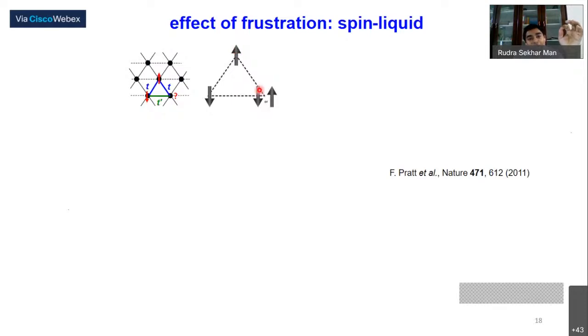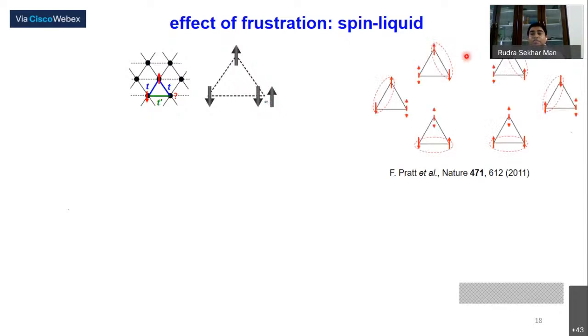And if you put down here, then this interaction is antiferromagnet, which is fine, but that one is ferromagnet. It's a problem, because I told you the ground state should be antiferromagnet. If you take a sample, you always get the Curie-Weiss temperature as negative. That means antiferromagnet. But in a system having this kind of triangular lattice, you can have different degeneracies.